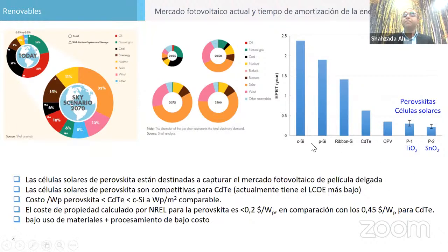If you look at the energy payback time, of course, this differs from area to area. In the north of Europe, it will be different. In the south of Europe, where there is more sun, it will be lower. But just to give you a relative comparison, it is crystalline silicon, then polycrystalline silicon ribbon. It is the lower for organic photovoltaic and lowest for perovskite solar cells. Due to the material usage, the energy payback time will be less because of the thickness of the material used and the energy consumed during the fabrication of this process.